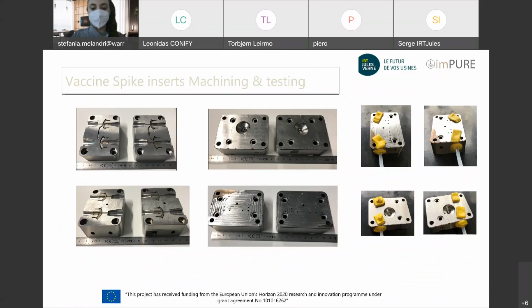Okay, so at the end, you see the final insert. We delivered just yesterday 2 sets of inserts, two upper and two lower inserts. Of course, you see we have some areas that are not perfect. We also have to optimize the dimensioning and the best fitting before machining.